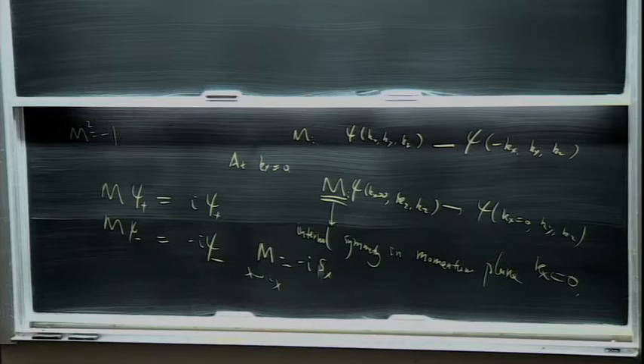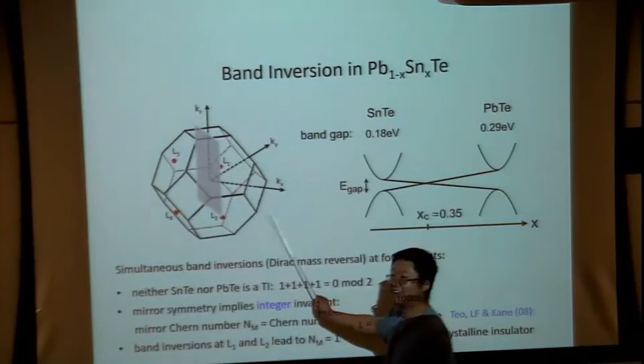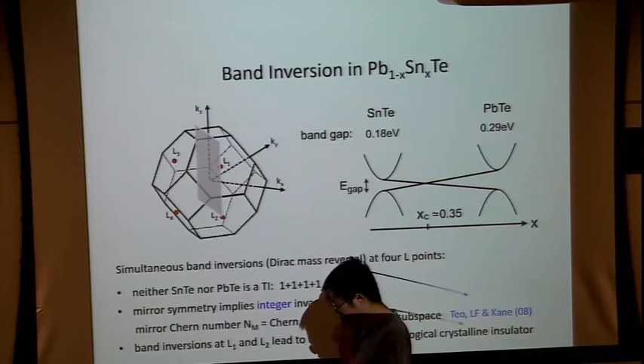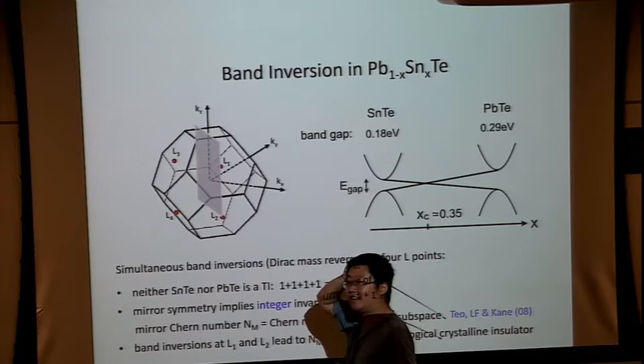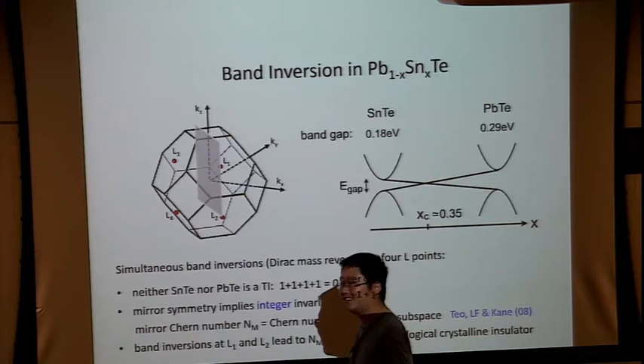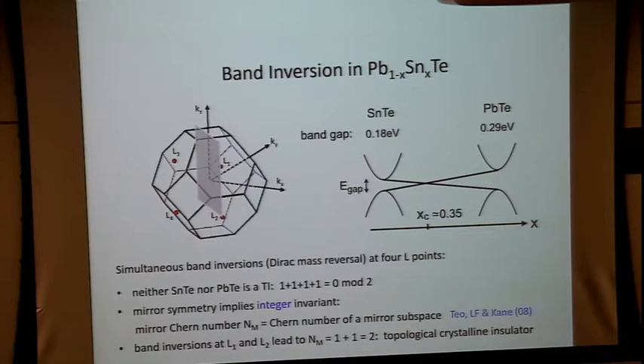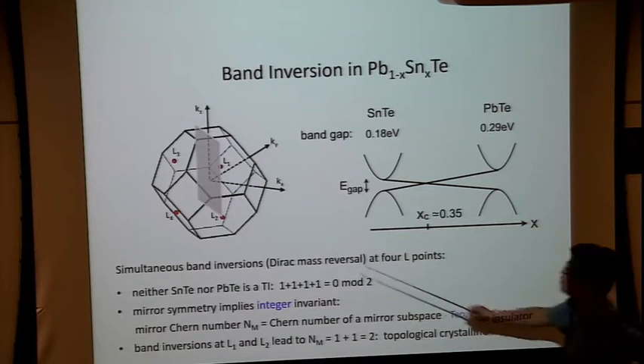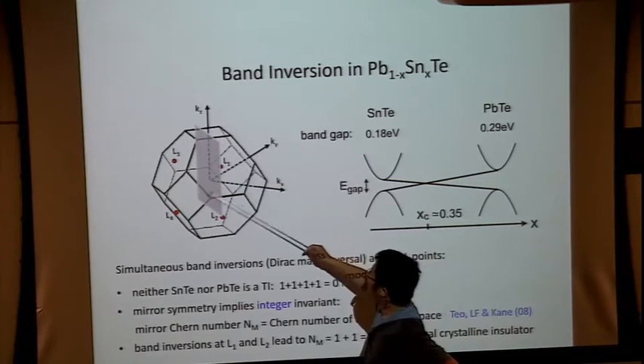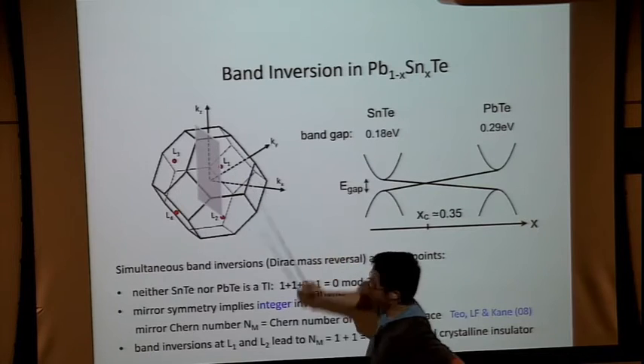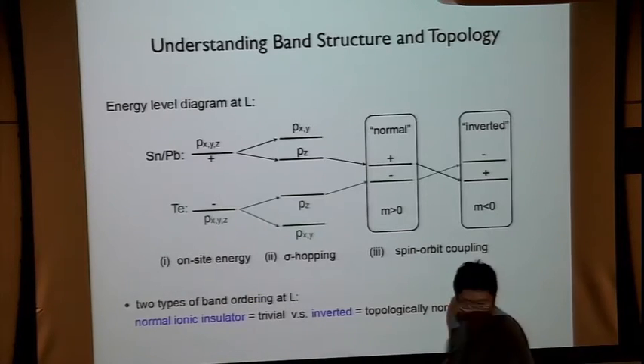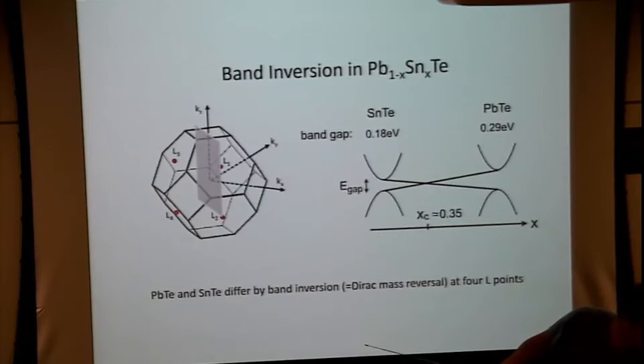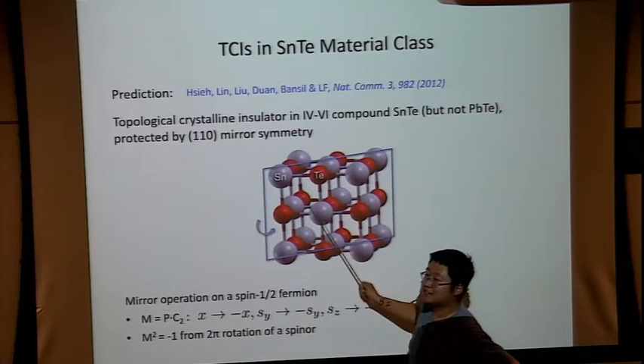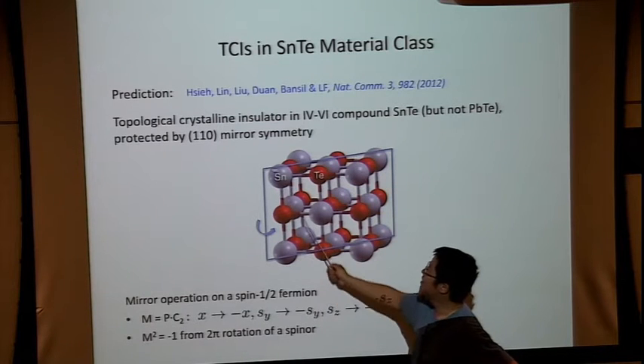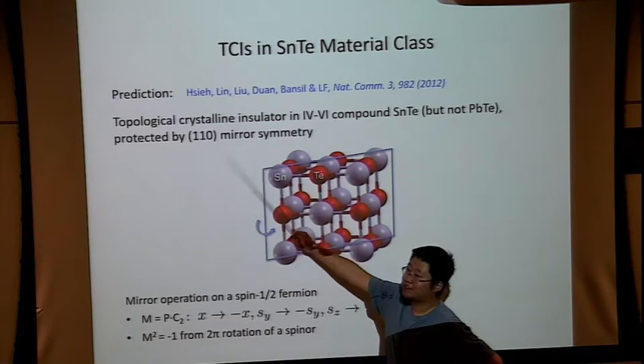Actually, that's an excellent question. For this particular rock salt structure, ky equal pi is the same as ky equals 0, and kx equal pi is the same as well. This is special to this rock salt structure. So L1 and L2 lie on the mirror reflection plane. Let me define it properly. The reflection plane is along the (1,1,0) axis, but there are equivalent reflection planes about (1,-1,0), (0,1,1), (0,1,-1), etc.